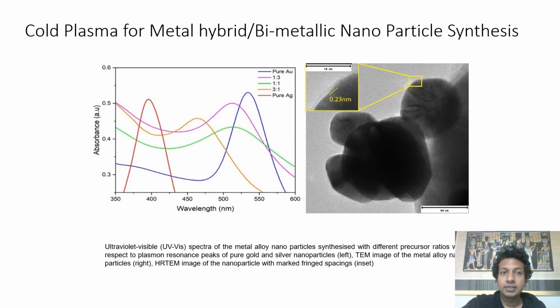Plasma-assisted nanomaterial synthetic techniques can also be used for metal alloy nanoparticle formation. Other than the general advantages such as efficient and low temperature production, plasma-assisted bimetallic nanoparticles result in well-alloyed yield with low aggregation properties. We have conducted some preliminary experiments with silver and gold bimetallic nanoparticles and obtained some promising results. This can be continued with other metallic atoms as well, such as platinum, palladium, which can be used for many other interesting applications.